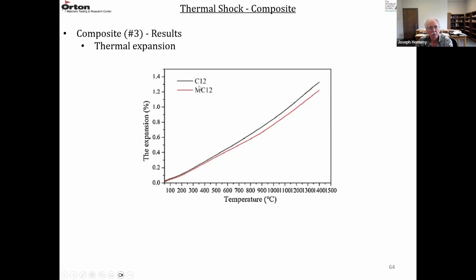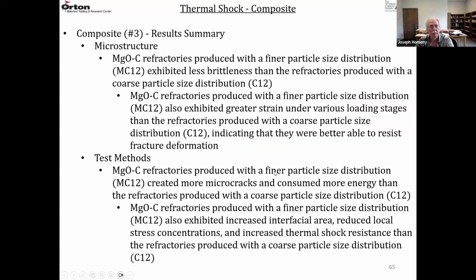They measured the thermal expansion, C12 versus MC12. So the finer material is in red. So going to a finer grain size actually lowered the thermal expansion of the composite a little bit, which also enhances the thermal shock behavior. Any material that has a decreased thermal expansion will have better thermal shock behavior.